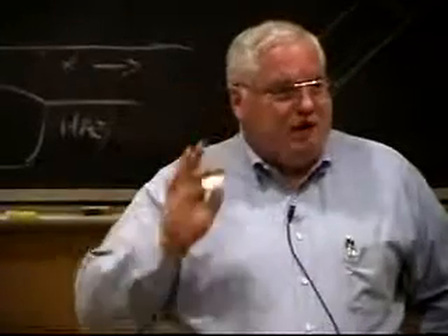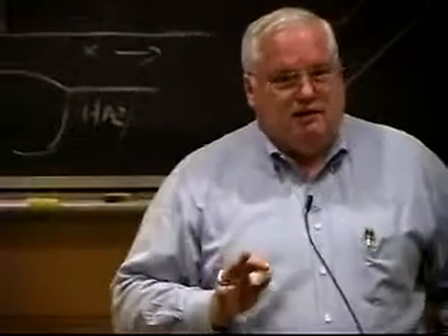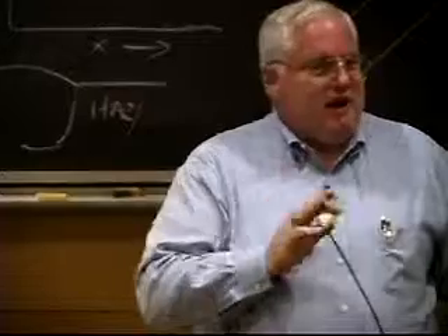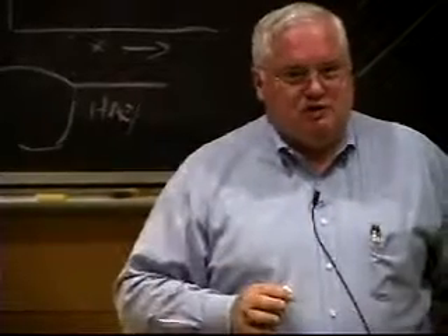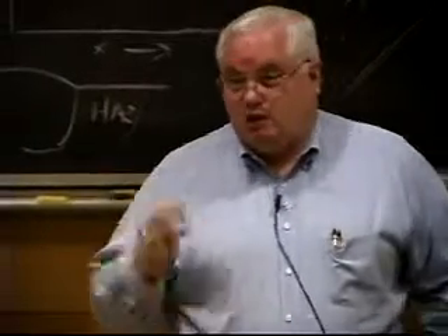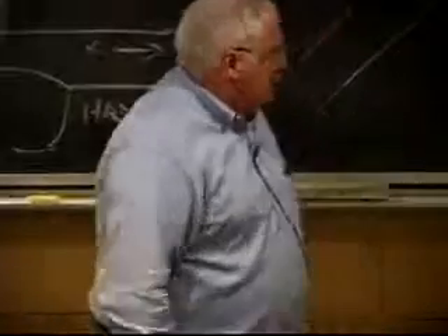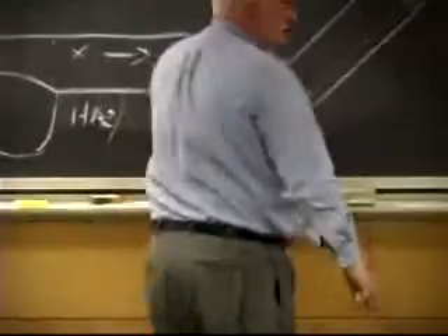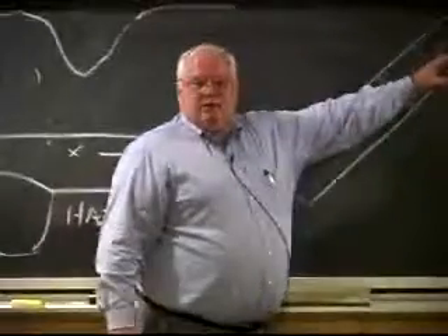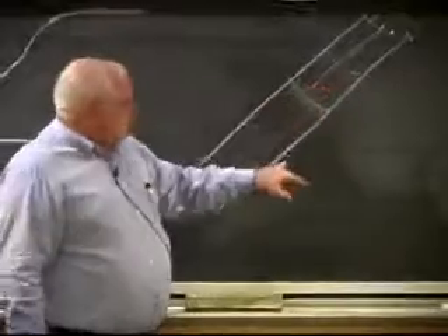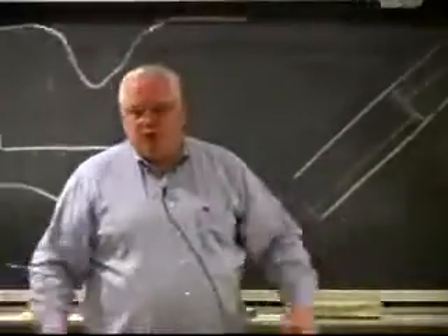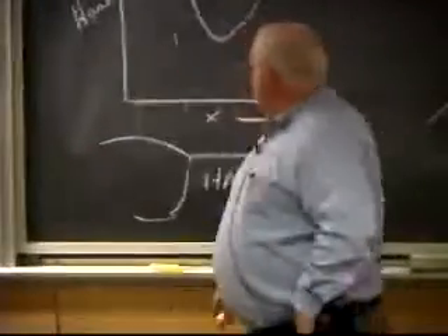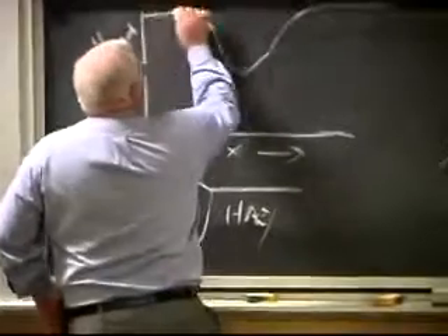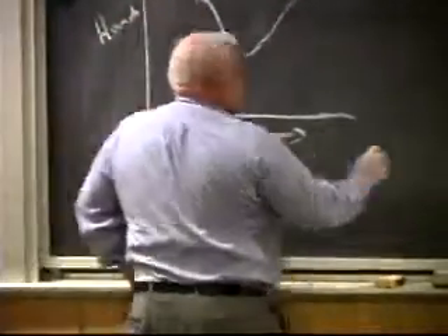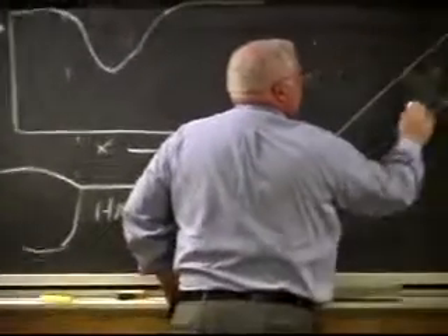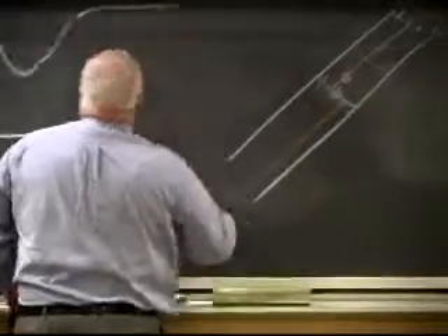And so when someone finally realized 25 years later that the fabricators had added an extra weld that wasn't in the original design, and realized that aluminum alloys don't have the same strength welds, they said, oh gee, is this thing going to fall down? Of course, they went back out and they welded gussets in to protect those welds, but they cut out a couple of samples and they wanted me to evaluate how weak these welds were. Turns out we did a hardness traverse, and we had some welds from the longitudinal welds, and some of the circumferential welds.